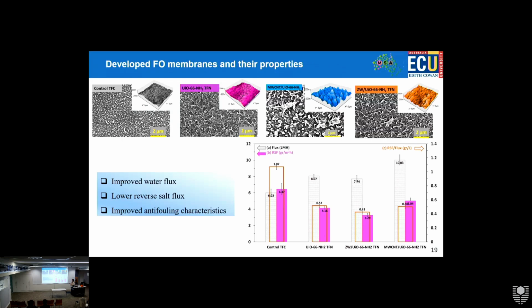So in here, again, the control and the 3 different types of membranes in their optimized concentration of integration of these materials are presented. As you can see, the surface features have changed after addition of different materials. And in here, the performance results in terms of flux improvement, reverse salt flux, that we mentioned is the back diffusion. We don't want that, so it should be minimum. And then reverse salt flux to flux. So if this is the lowest amount, this is the best case.